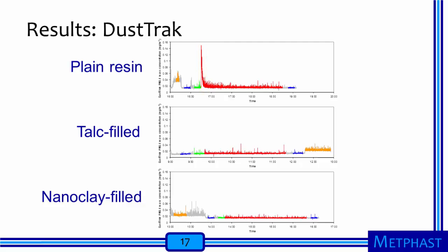This spike is probably due to the granulator having some large particles from a previous study attached to its blades that did not come off until we started shredding our test plaques. We can see that concentrations fall back down to background levels very quickly following the spike. Overall, the mass concentration data suggests that few large particles were generated during shredding because they would be the ones that would contribute to an increase in mass concentrations.